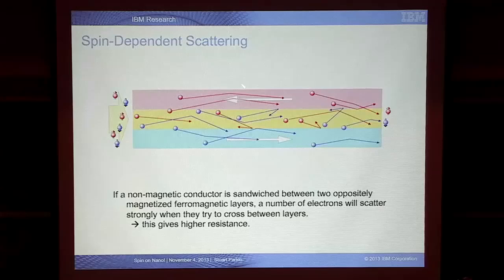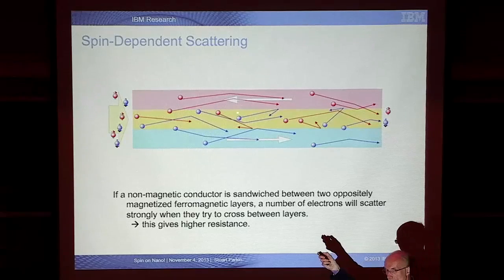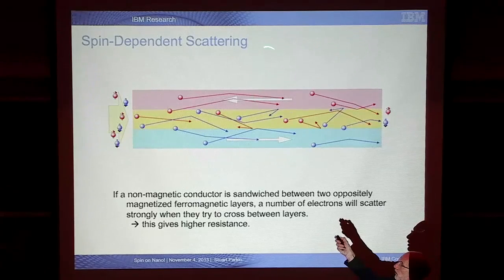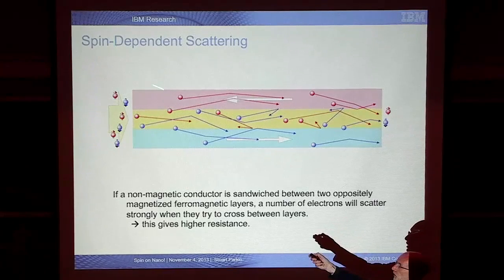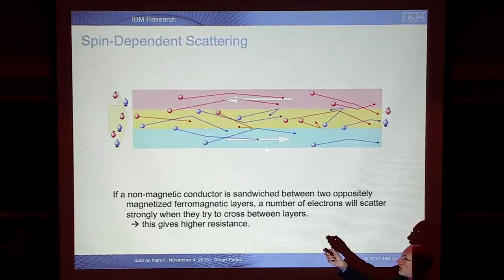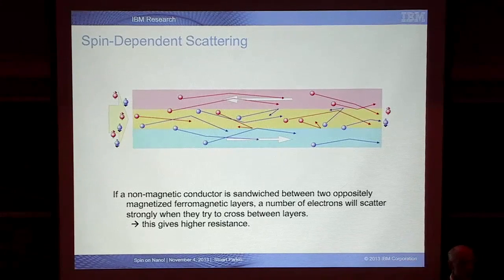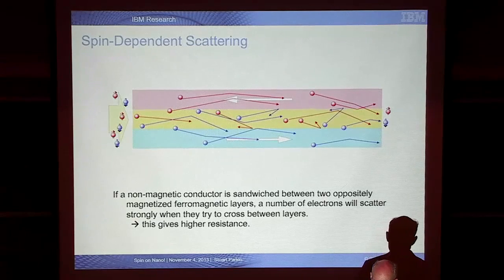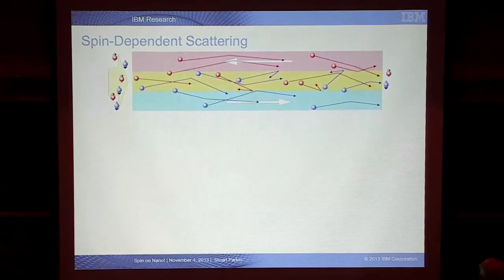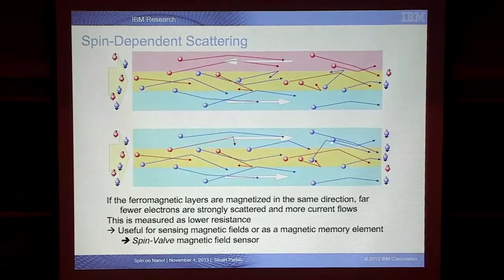The electrons will be passing all over these layers. And so these blue electrons, which were least strongly scattered here, will cross this relatively thin copper layer and will be scattered in the top red layer. And the red electrons, which like this red layer, will eventually see this blue layer and be strongly scattered. So all the electrons, no matter where they are, will eventually be scattered, and the resistance of this structure will be high compared to the case in which we have the same sandwich of two magnetic layers, but in this case, the magnetic moments of these layers are aligned parallel to each other.